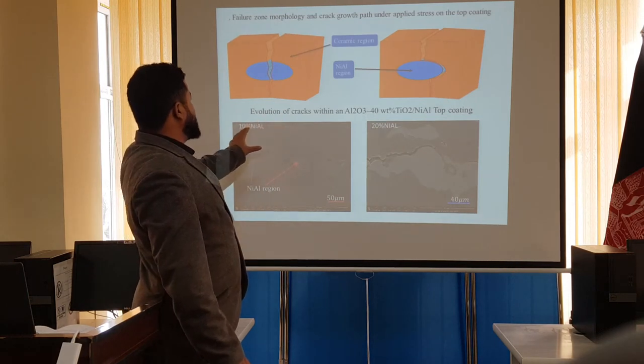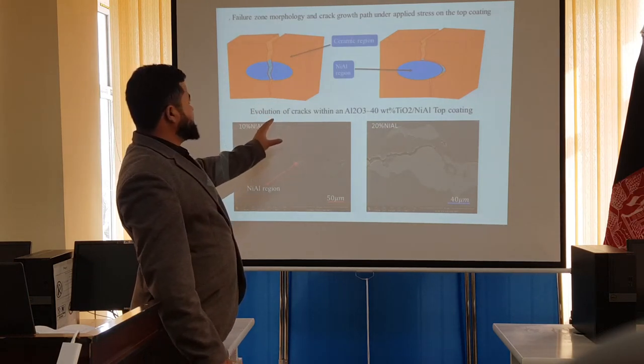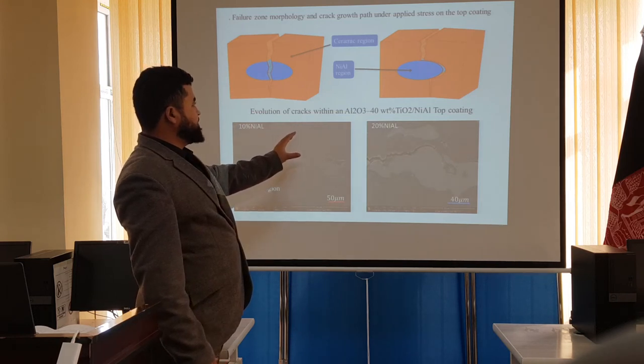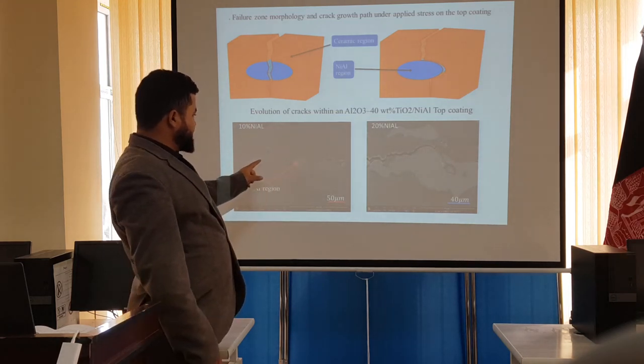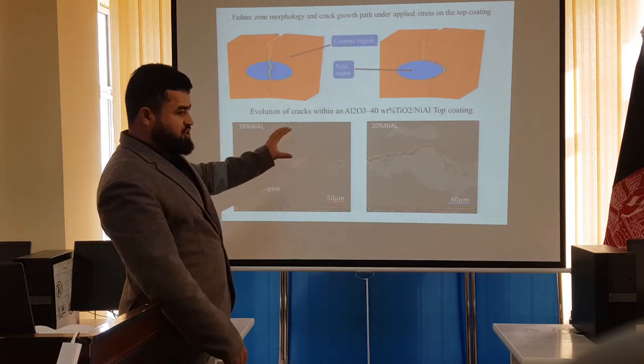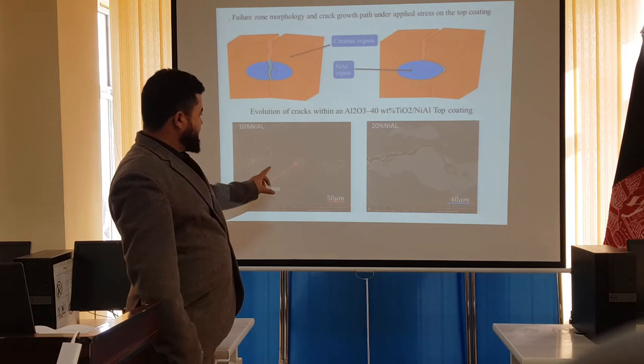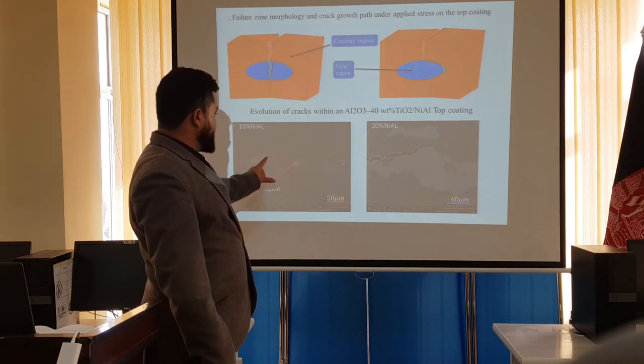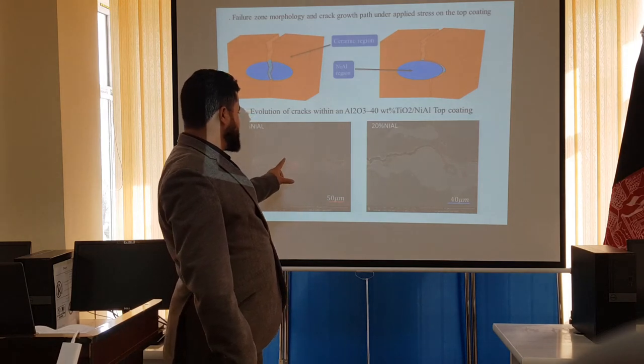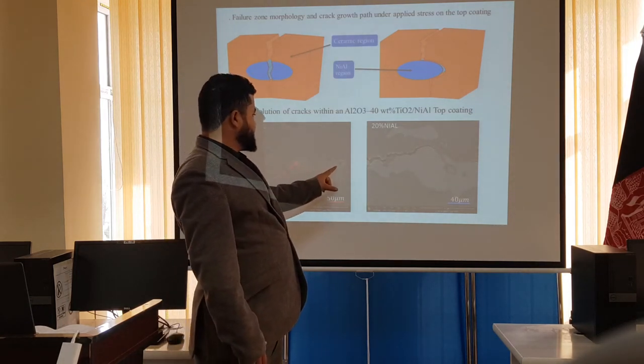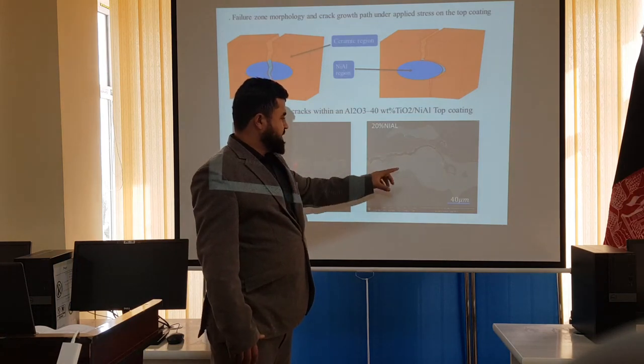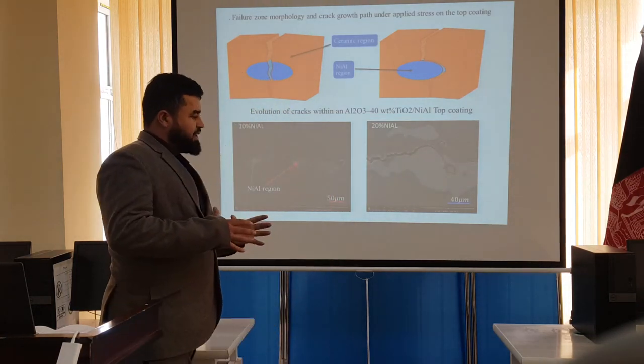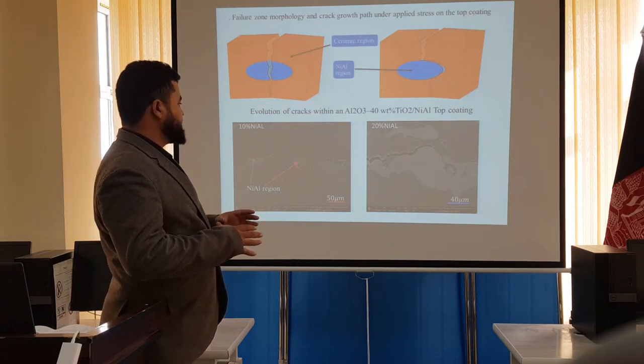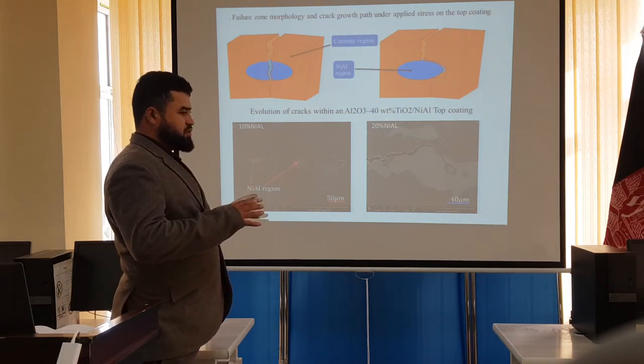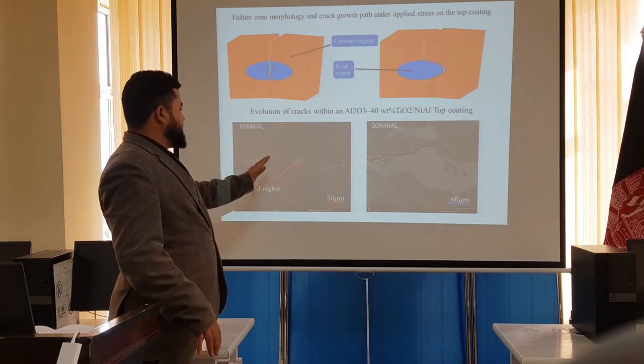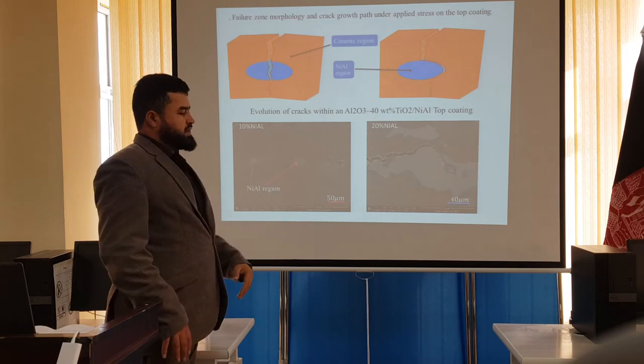We can see here a failure zone of morphology and crack growth under the stress on the top coating. After the Vickers hardness test, we got this SEM picture from the cross section. We can see the cracks grow directly toward the ceramic area, then change direction going to the interface. It means nickel aluminum doping has a good effect on our 8040 plasma ceramic coating because it resists the propagation of cracks.